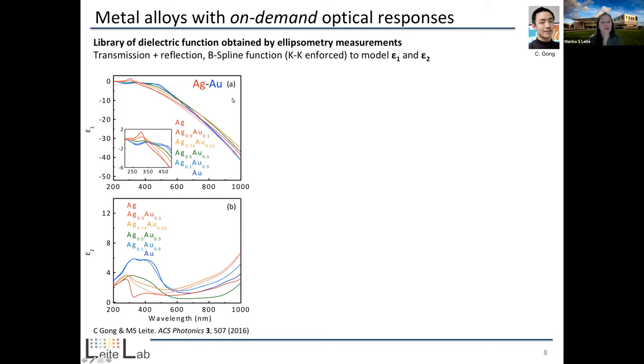So basically, there's quite a bit of data in this slide. I won't go into all the details, but I just want to highlight that what we've noticed here when measuring reflection and transmission and modeling the permittivity of silver and gold is that despite the fact that this binary mixture forms a solid solution regardless of its chemical composition, meaning the enthalpy of formation is negative, basically, what happens is that we do have quite a lot of variation in n and k, and it's very nonlinear.